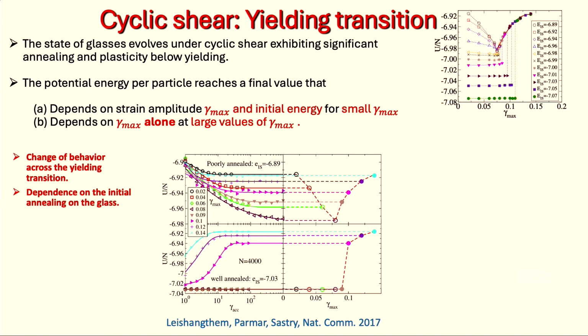All right. Now, this is a larger set of results showing the same thing as a function of the initial energy of the glass. I have a very different way of going through the yielding transition. For poorly annealed glasses, I have mechanically induced annealing before yielding happens and the energy begins to go up.